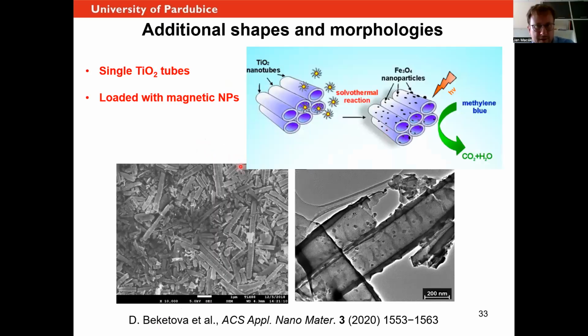Here, just a few words about the single tubes. They have been attractive very much, in my view, also in the view of the audience that uses these powders, because we were in principle doing this first for biomedical people who wanted to try to see some drug deliveries, like use these tubes as drug carriers or nanorobots. So we tried to do these single tubes, and we also managed to decorate them with superparamagnetic nanoparticles. And so we grew tubes, etched the tubes to have powders, and then we did the Massart reaction to make magnetic nanoparticles on the surface.